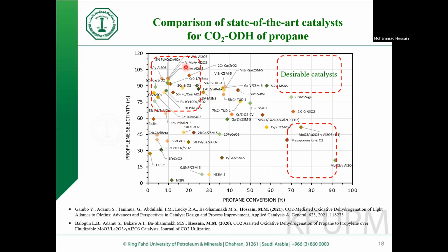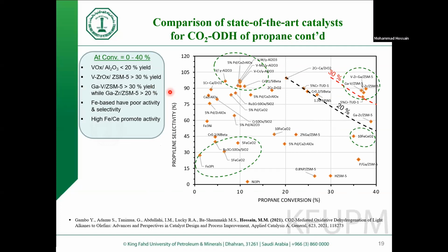Now, in order to further evaluate these catalysts, one can consider calculating yield. And here we can see the yield for some of those catalysts. In this case, vanadium on alumina yield is less than 20%. And when vanadium was promoted with zirconia and deposited on ZSM-5, yield reached about 30%. Gallium also can play an interesting role on vanadium-based catalysts to achieve a 30% yield. Iron has been shown to have poor activity and selectivity. However, when it's combined with ceria, it shows some good activity.